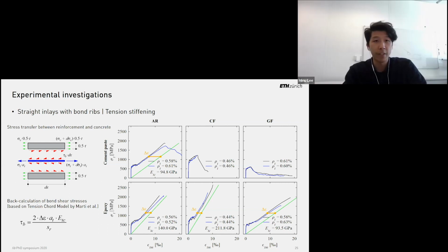So the aramid fibers are much less sensitive to lateral loading. If you handle the fiber materials or the rovings directly, you can see from taking them into hand that with aramid fibers you can actually make knots or really bend or fold them with a bending angle of 180 degrees, and more or less nothing happens. But the glass fibers really just break. If you make a knot into them, the knot will not hold.